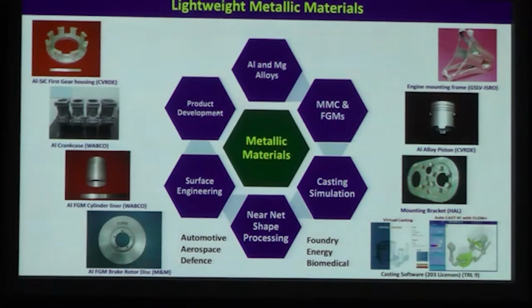And a couple of other products are with automotive industries, especially the aluminum crankcase and the aluminum FGM cylinder liner. In the case of the aluminum crankcase, earlier they had been using cast iron systems, which have heavier weight. So to reduce the weight, we went for the introduction of aluminum silicon alloys. And these aluminum functionally graded cylinder liners are being imported from Germany, and our duty was to make high wear resistant cylinder liners. Here we used the centrifugal casting technique, with a high silicon alloy, which is A390 alloy having higher silicon.